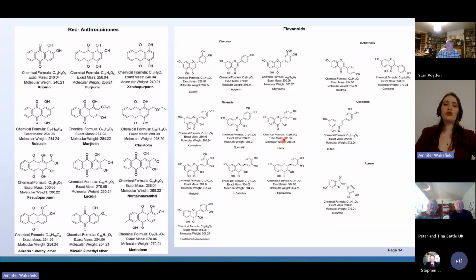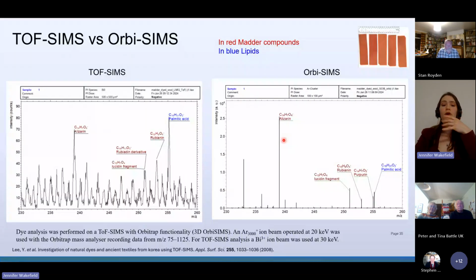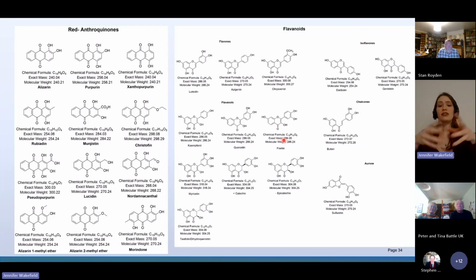So ideally, what you do is take a sample specifically exactly where you want on the tunic, for example, and you can identify the color of the tunic. And you can then take a sample from one of the boxes in worse condition and narrow down exactly what plant was used. So doing a combination where you can get the suitable size.